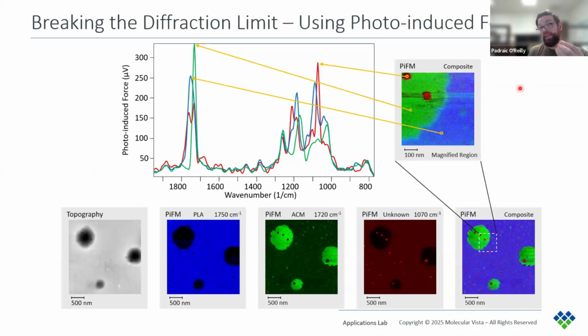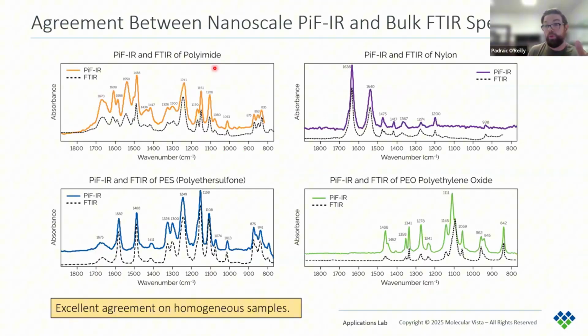Now, the other way of measuring the chemical information is via a spectrum. So in this case, the tip is moved to a specific location on the sample surface. The IR laser is swept through its range, and the response of the cantilever is recorded. So the stronger the response at a specific wave number, the taller this peak in the spectrum will be. And this is directly related to the FTIR spectrum, which is what we see here.